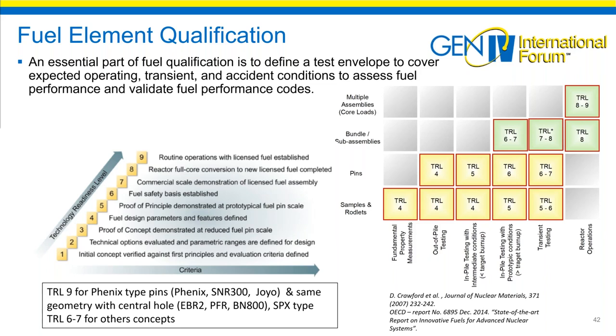From level 1 to 2, it's a selection phase. The 3 to 4, it's development, so mainly R&D. And at level 4, starts the test for the qualifications. So you can see here that between 4 to 5, we have some tests at the pilot or pin scale with out-of-pile test. Then from level 5 to 6, we have to test under representative conditions with a representative composition and geometry. This means at pin level.